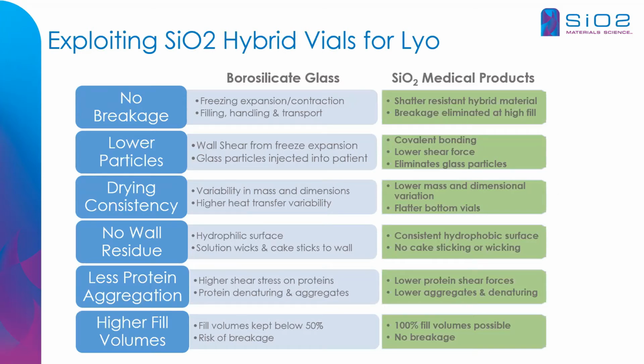We've also found that we have lower subvisible particles, particles that could be created during shear forces in the containers. We will show you some data that compares subvisible particles after freeze drying in our container versus a glass container. And another important one is drying consistency. Because we have very uniform wall thickness, tight tolerances, and certainly the mass consistency, the weight-to-weight variation of our containers is much tighter than glass containers.